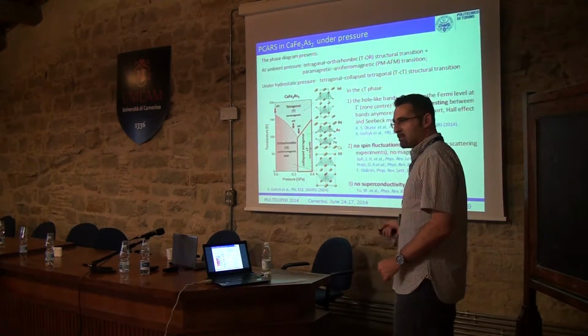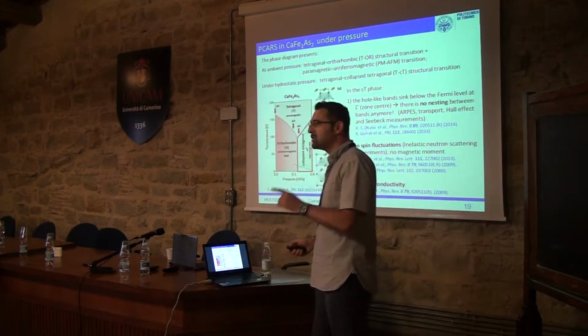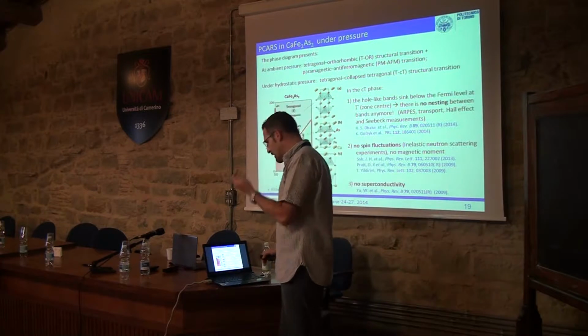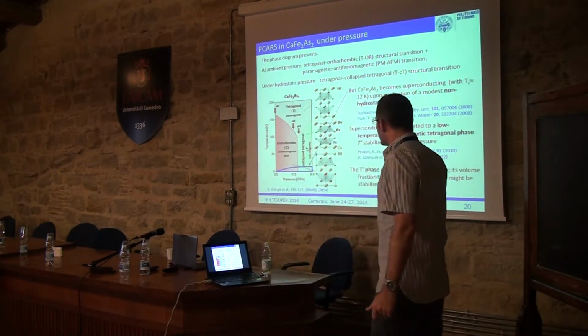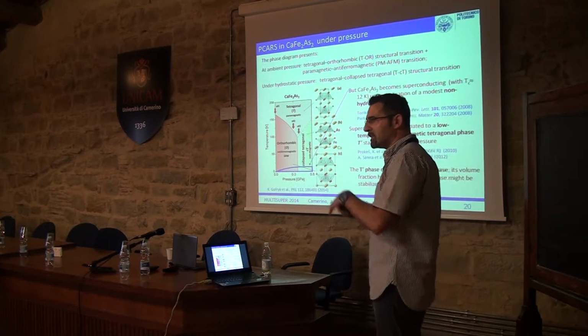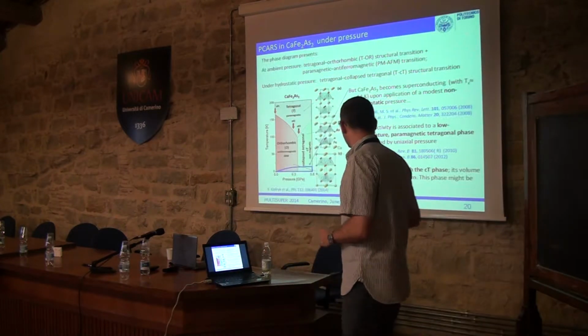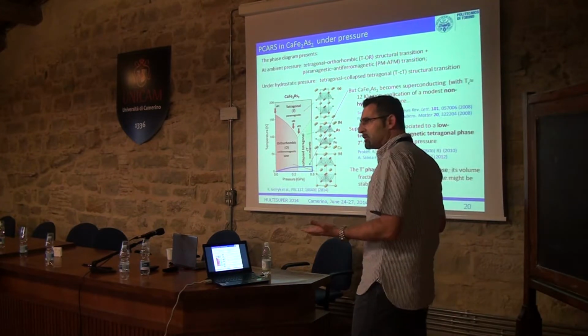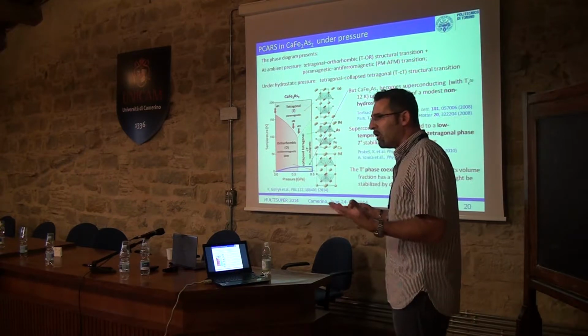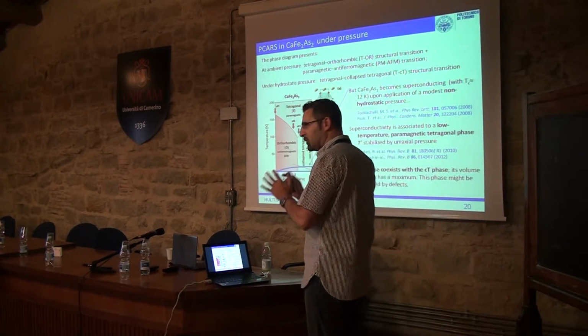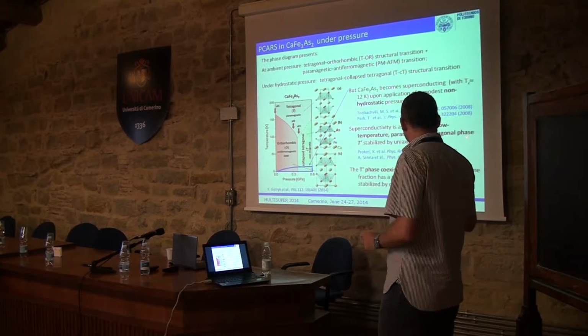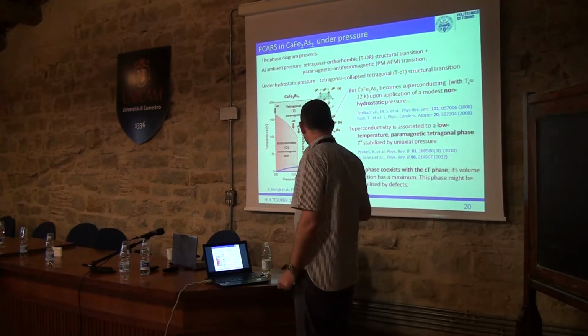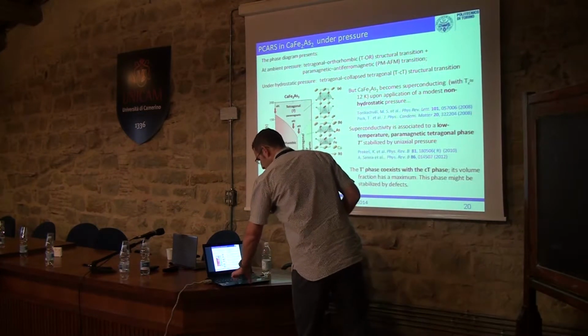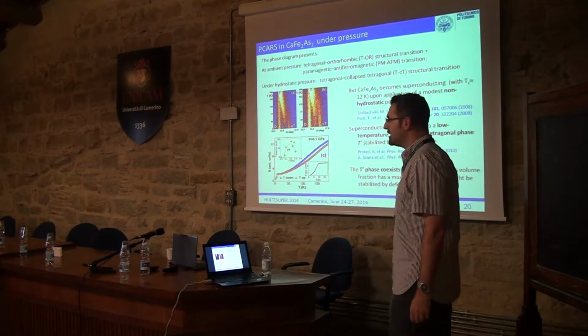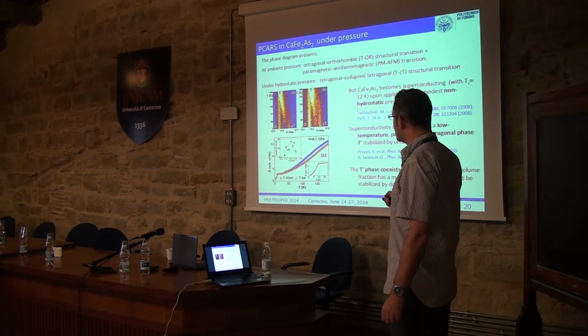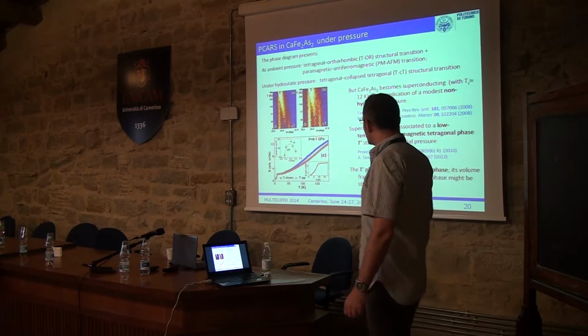But this system is superconducting under pressure, provided that the pressure is not completely hydrostatic. If you have at least one uniaxial component, you can observe superconductivity, and it is always confined to a small volume fraction, as we have seen before. It's thought that this superconductivity is associated with a tetragonal phase which is not collapsed, still paramagnetic, and that hosts superconductivity. This T prime phase coexists with the collapsed tetragonal phase. These are XRD data. You see that this is the orthorhombic, this is T prime, and this is the collapsed tetragonal phase.